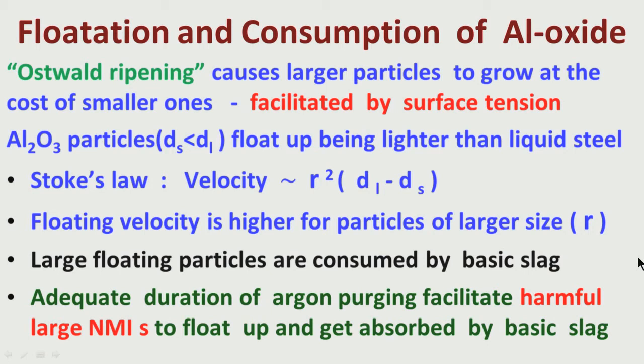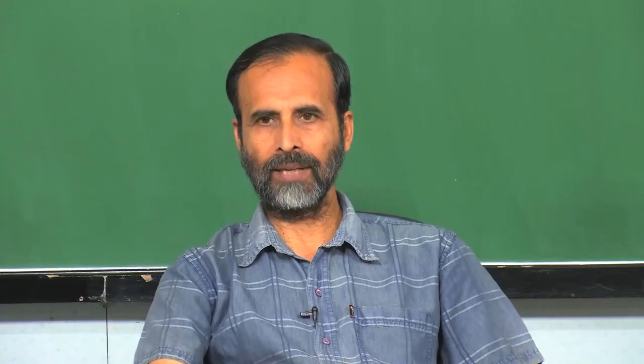So I have told you how these alumina oxides are forming. That means you are adding aluminium as deoxidant, and it is causing the dissolved oxygen to come down. So we have dissolved oxygen and dissolved aluminum in steel, as well as alumina as particles. These alumina particles will try to float up, they will try to coagulate and become bigger, and then the bigger particles will float up. This process is enhanced by the use of argon purging, because it helps the larger particles to form faster and go up, float up and get absorbed by the slag which is basic in nature.